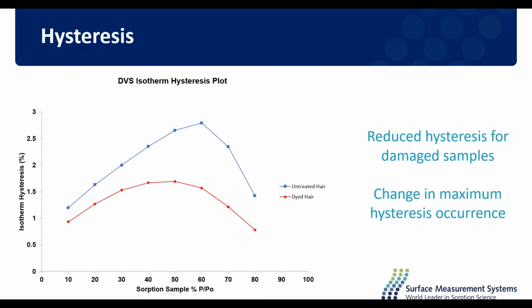So now, finally, let's have a look at hysteresis. And I'm starting with just looking at the hysteresis for the untreated hair and for the dyed hair. And we can see initially and quite clearly that there's reduced hysteresis for the dyed hair sample. And we can also see that the maxima hysteresis, the occurrence of maxima hysteresis, for untreated hair is at about 60% relative humidity. But for the dyed hair sample, it's moved to about 50% relative humidity.